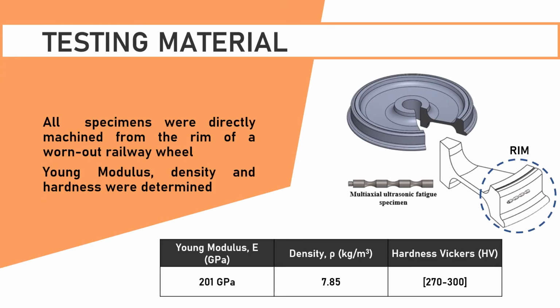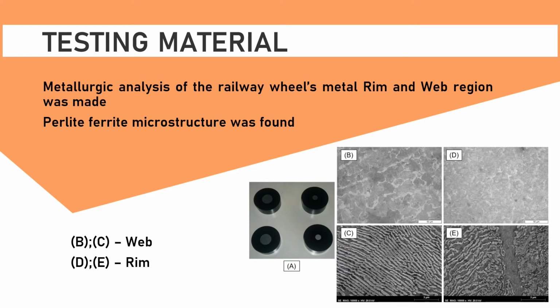Taking a look at the wheel in analysis, we made first a few tests to determine the Young's modulus, the density, and the hardness of the rim section, where we later machined the specimen directly as represented in the image. The metallurgic analysis of the rim as well as the web, since they are the main sections of the wheel, determined a pearlite and ferrite microstructure. This analysis was very important to later understand the results we obtained in the ultrasonic fatigue test.